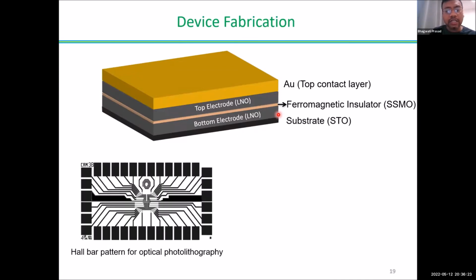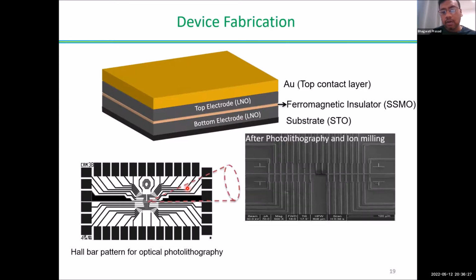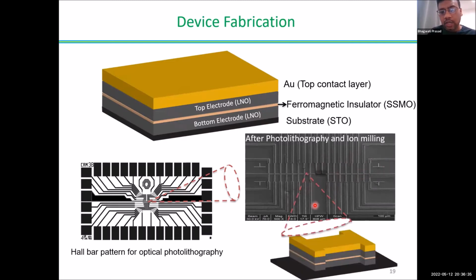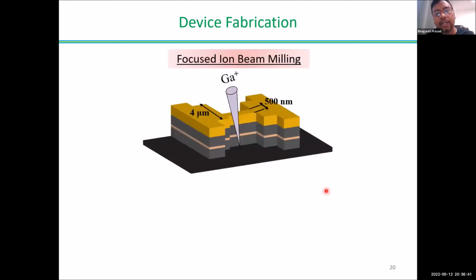Then we use the Hall bar pattern for optical photolithography, and that's how it looked after photolithography and ion milling. You see the series of 4 micron tracks here, and then here you can make your one device. You can make around 14-15 devices in one chip, and then you further narrow down those tracks from 4 micron to like 500 nanometers by focused ion beam nanomachining technique.